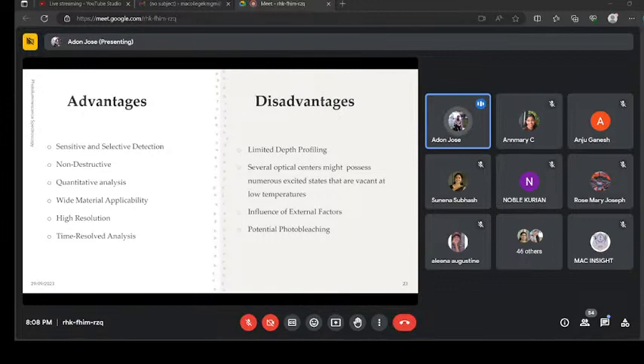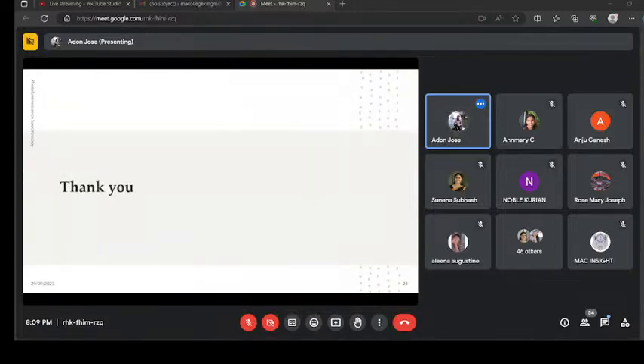The other major disadvantage is the influence of external factors. Actually, environmental factors such as temperature, humidity and ambient light can influence the PL measurements, so we have to be careful to control them during experiments. And the other factor is potential photo bleaching. That means some materials are prone to photo bleaching. Prolonged exposure to light during measurements can alter the luminescent properties of the sample, which may affect the accuracy of the results. So that's it. Thank you.